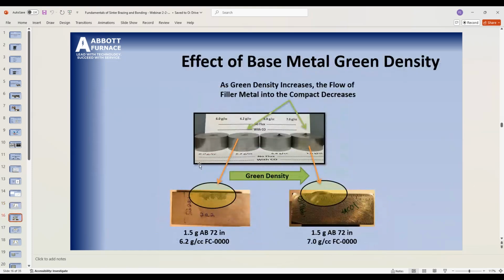Well, if we look at it, we know that density is important. And so what we did is we have from left to right, we have a 6.0, 6.2, 6.8, and 7.0 density. And we put a tablet on top. And you notice, as we go to the right, you can see that filler metal pellet melted, and at the higher density, it didn't infiltrate because it filled the pores and there was nowhere else for it to go, right? And if we section it, you can actually see where at the lower density, it actually went into the part as opposed to the high density where it sat on the surface. So our density is important. So what we want is we don't want a real low density because we've got a lot of time where it can steal it. We'd like to have higher densities so that it fills the surface quickly and holds the rest of that filler metal in the gap.